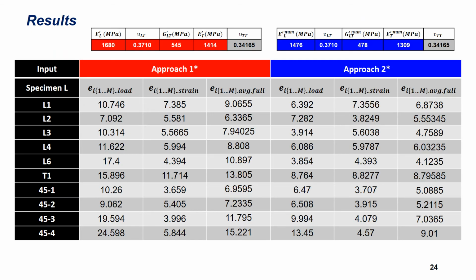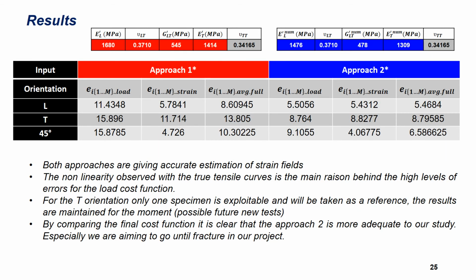Here are the results for valid specimens. Sadly, for the transverse direction, only one specimen is valid. To compare both approaches: first, both approaches are giving accurate estimation of the strain field. The nonlinearity observed with the true tensile curves is the main reason behind the high levels of error for the load cost functions with both approaches. But the second approach is still giving lower error values.